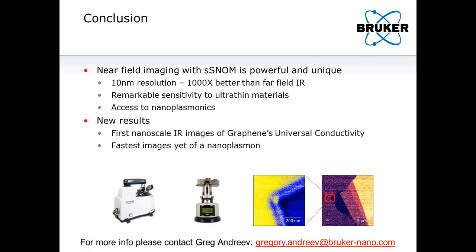A question here about semiconducting materials: can you obtain information about them? Yeah, you can. With semiconducting materials, if you choose a very long wavelength, like 11.5 or 12 micron wavelength, you can actually access the plasmon resonance of a semiconductor. You can look at the Drude contribution to the infrared reflection and get information about the charge density. You see contrasts between a charge density of, say, 10 to the 18 to 10 to the 19 very clearly, and that's shown in the work by Andy Huber that I referred to earlier. You can get a lot more information in his papers.